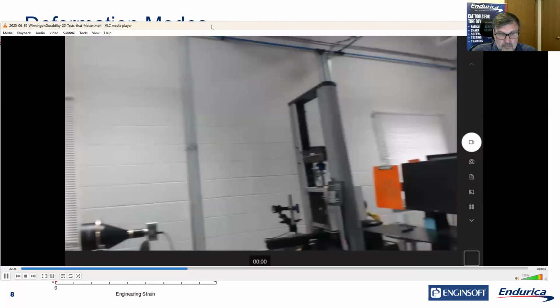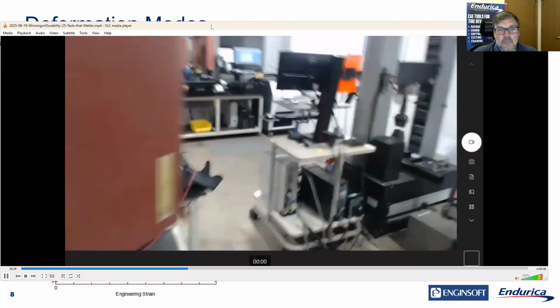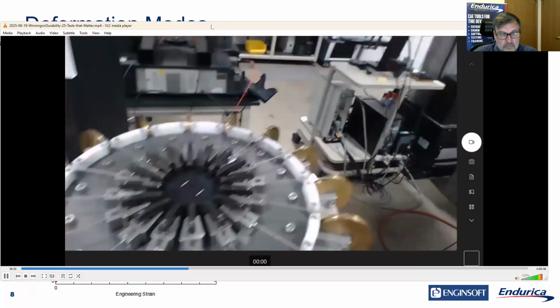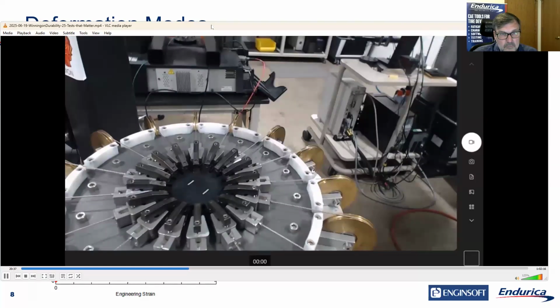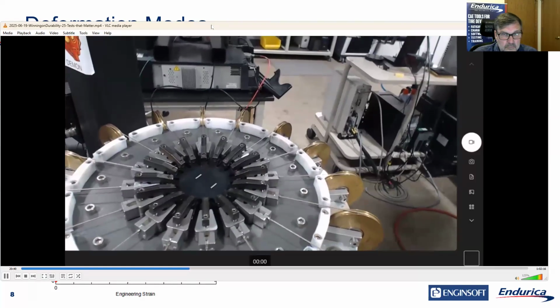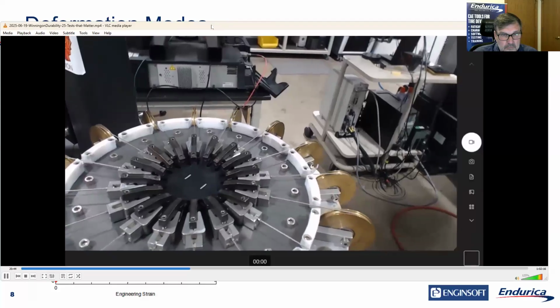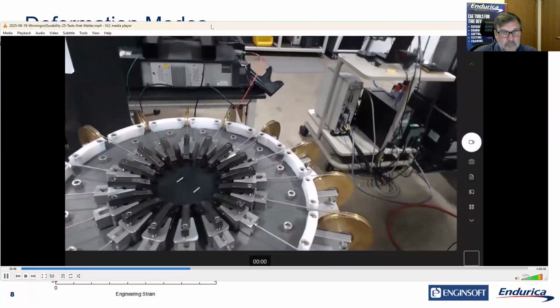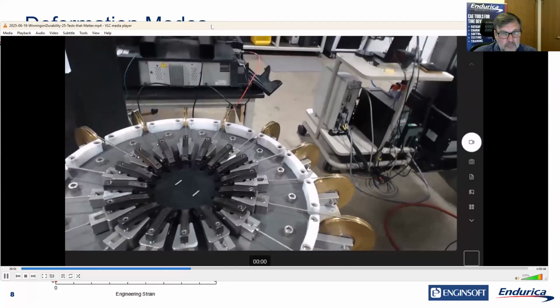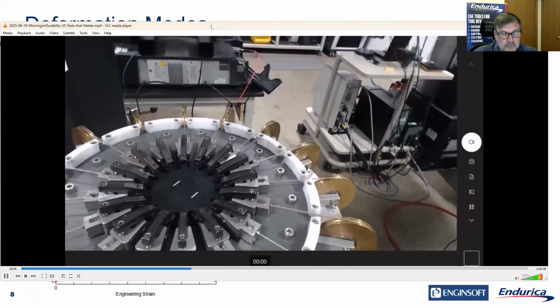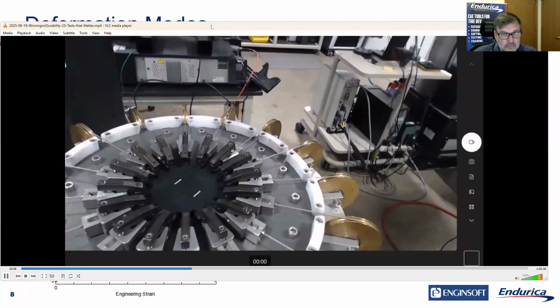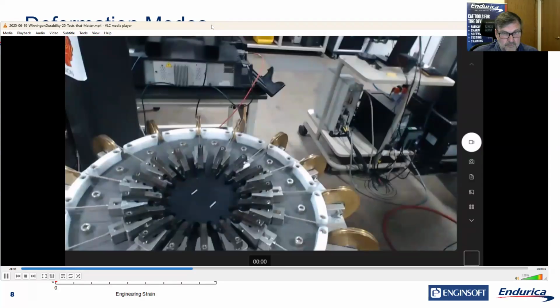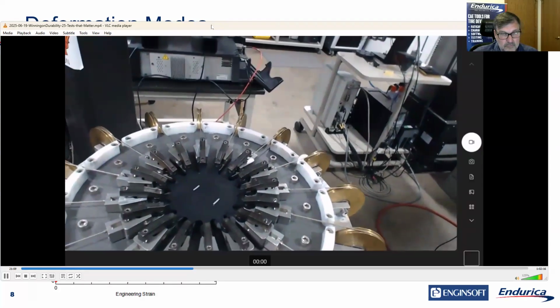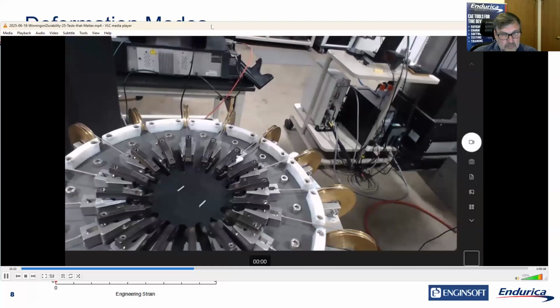And so I'm going to rotate the camera here. What we have going on is a biaxial test running. Let's see how I do here. The two stickers on the surface are to measure strain, and the entire region in the specimen is all being equally biaxially stretched. Honestly, we could measure strain between any two points we want. So once again, there's a laser extensometer looking down on the surface. So that's the biaxial test.